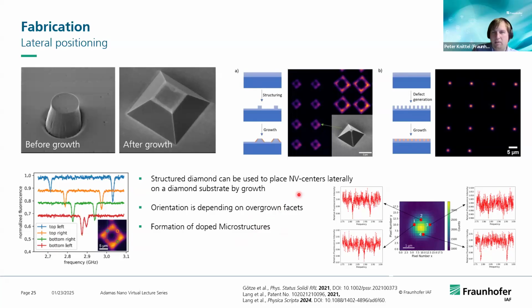In addition to that, you can make use of this in an inverted way. You can specifically generate defects in diamond and etch them, and this etching again leads to the formation of pyramids, but in this case inverted pyramids. By then growing on these 111 facets on the inverted pyramids, you can accurately place NV centers in these etched pits. You can even produce a smooth surface layer again.